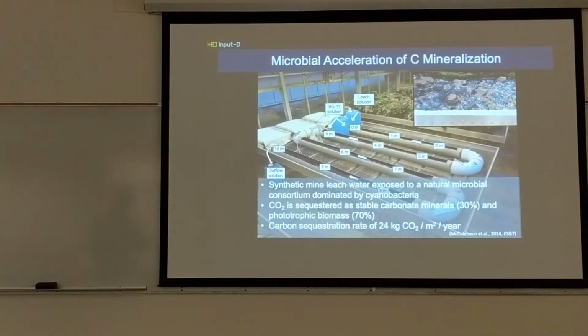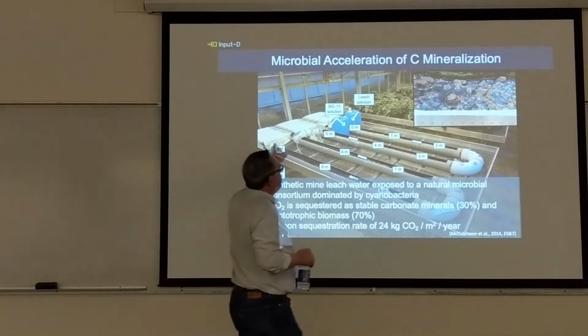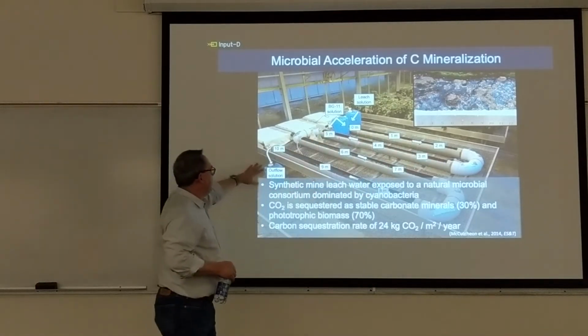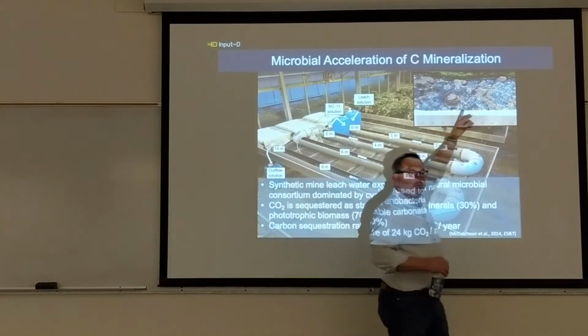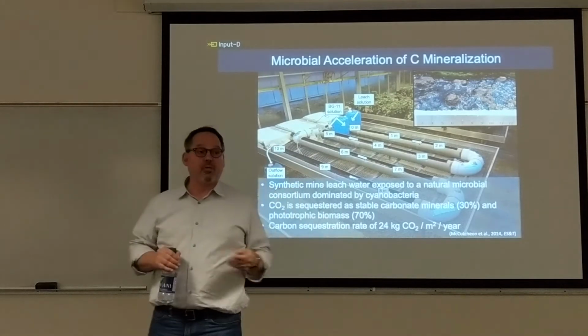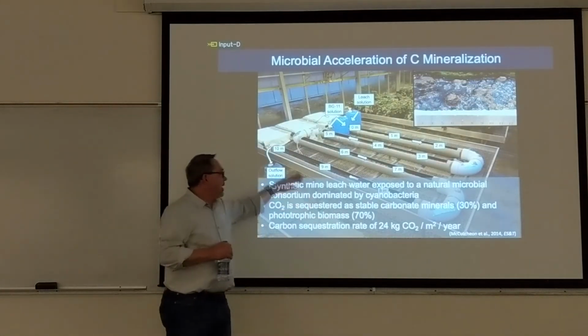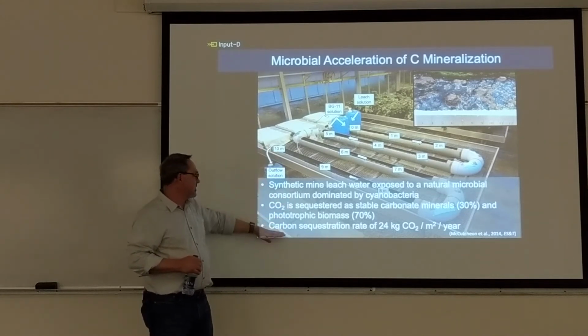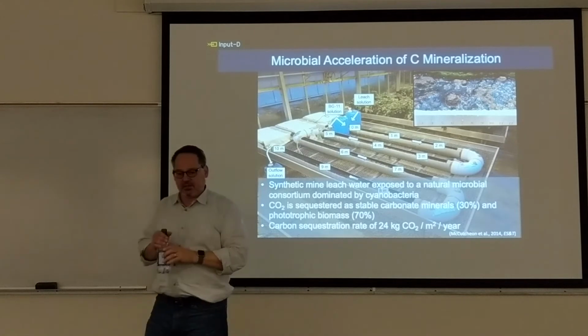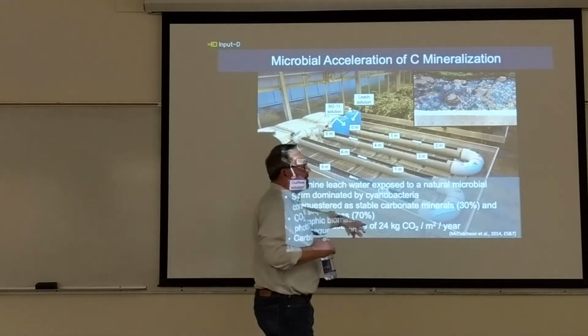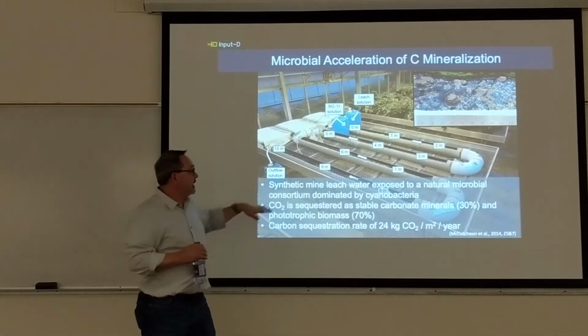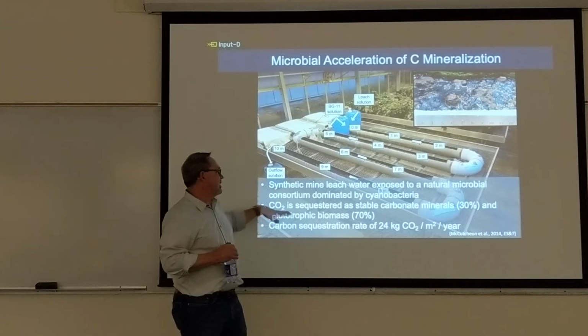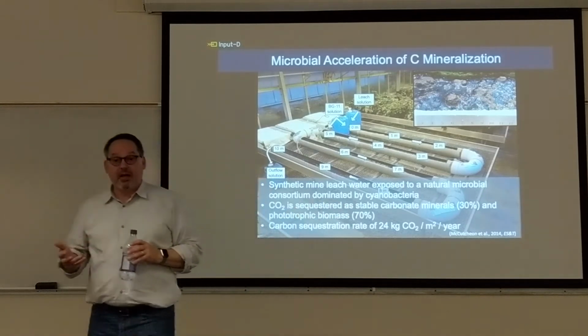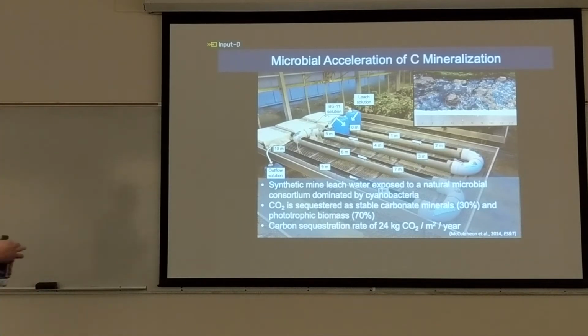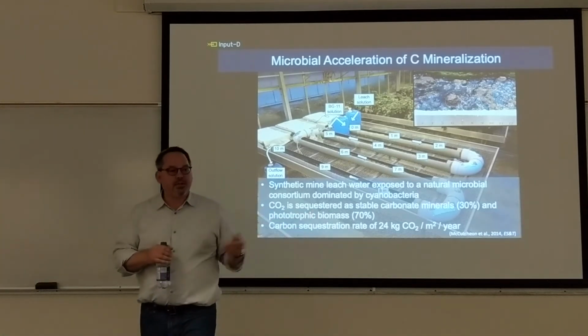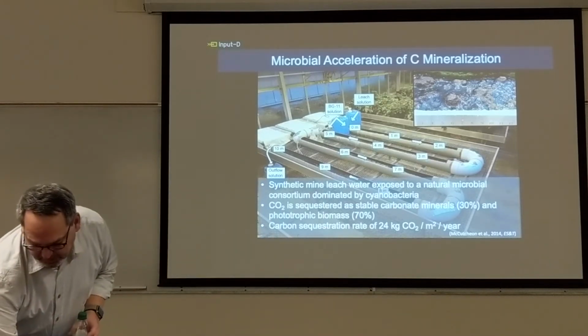A more extreme example is the master's thesis work of Janine McCutcheon. She basically made a 10-meter wetlands. This is basically synthetic mine leach water populated with algal mats from Atlin, BC, which is an area of natural weathering of ultramafic rocks. By using this synthetic wetlands, she was taking these solutions and got a carbon sequestration rate of 24 kilograms of CO2 per meter squared per year. Remember, the rate at Mount Keith is 2.4. So this is a 10-fold acceleration of the CO2 uptake rate, in this case by using photosynthetic algal mats. Only about 1/3 of that goes into minerals, 2/3 goes into biomass, but then there's the potential for biofuels, or potential value in the biomass that you're making. So this would be an example where you'd accelerate your CO2 uptake by using biology.